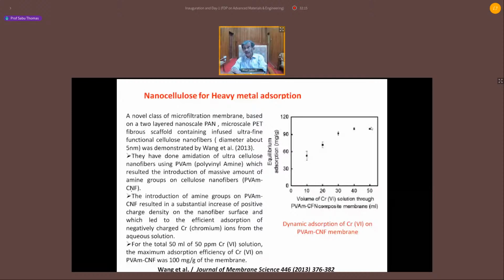But please remember that if you want to remove chromium, you have to do a little bit of surface chemistry on the nanocellulose. Then they made an amidation reaction. In the amidation reaction, they introduced a massive amount of amine groups on the surface of the nanocellulose. So nanocellulose became electropositive. And this electropositive nature of nanocellulose, high positive charge density on the nanofiber surface, led to the efficient adsorption of negatively charged chromium-6 ions. I can show you another important slide.